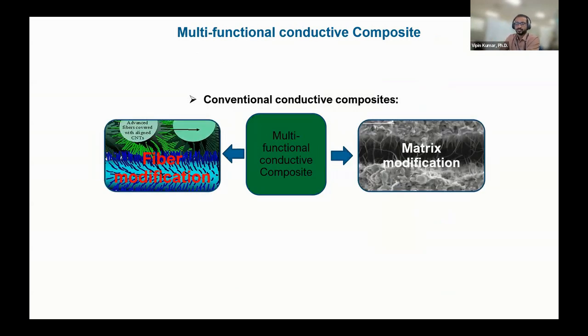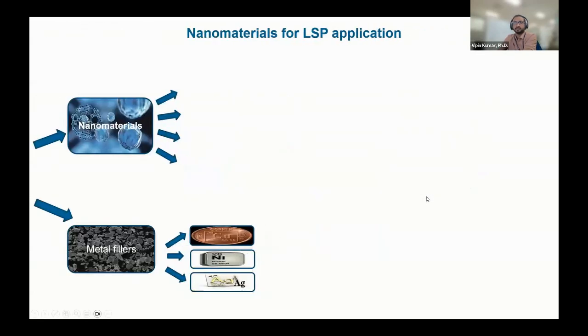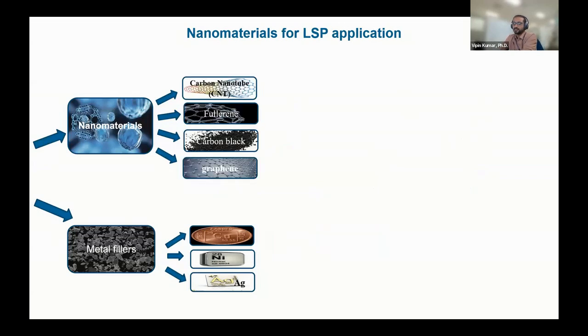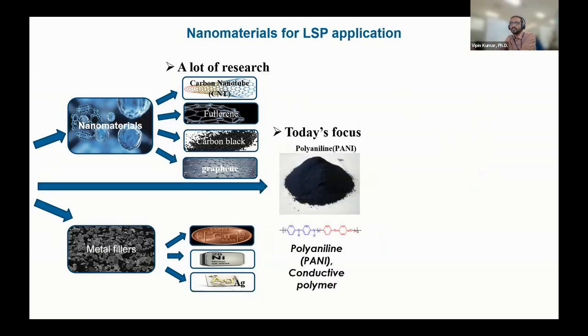You can either change your fiber interface, try to enhance a good connection between carbon to carbon, or you can modify the matrix, the resin system. Of course, modifying the fibers is more expensive and more complex than just adding fillers to a resin system, and that's what most people do. And I tried the same way. Until now, the focus on making a conductive composite has been adding nano fillers, carbon nanotubes, fullerene, carbon black, graphene. I went a little bit different, and I used a conjugated polymer named polyaniline, which can be made conductive. And I tried this method to see if I can make a composite electrically conductive.